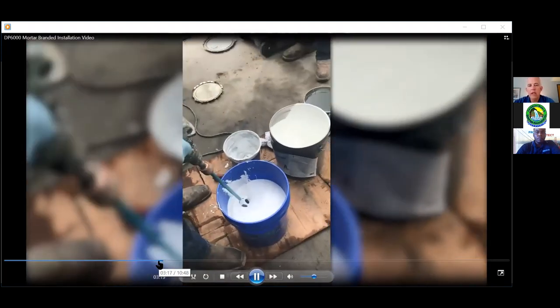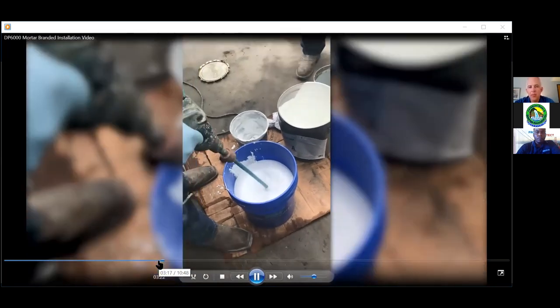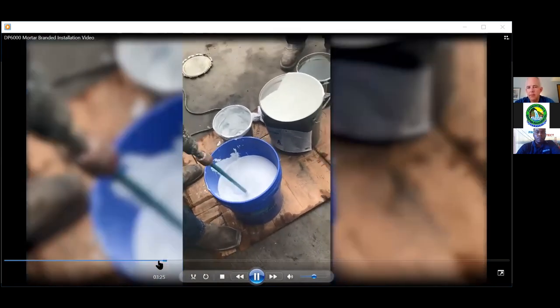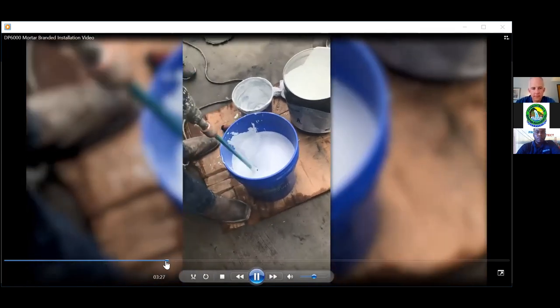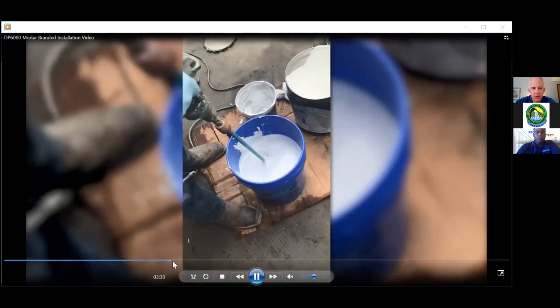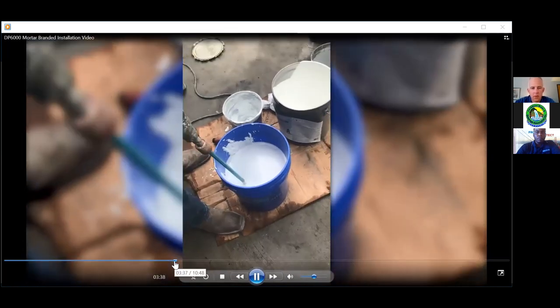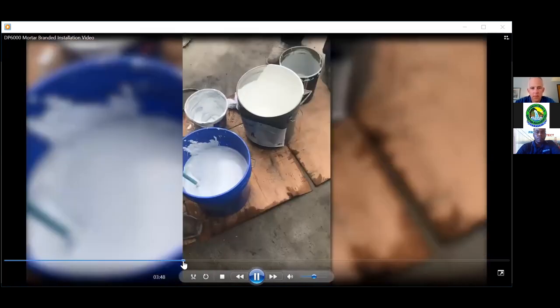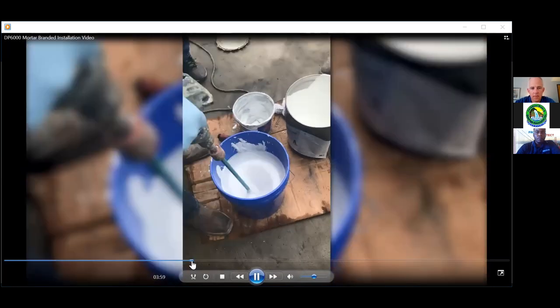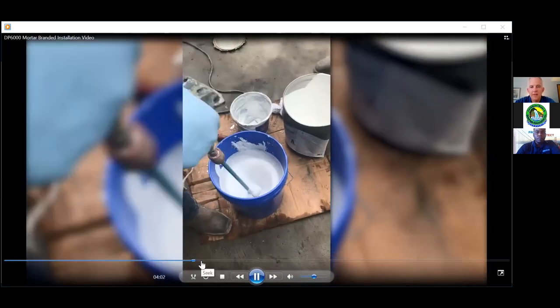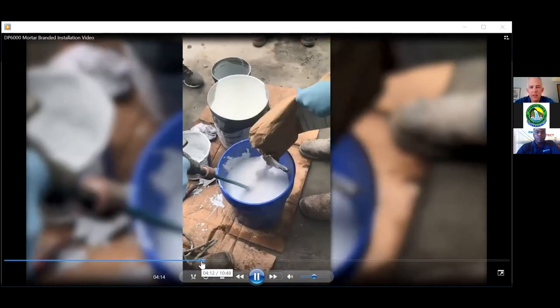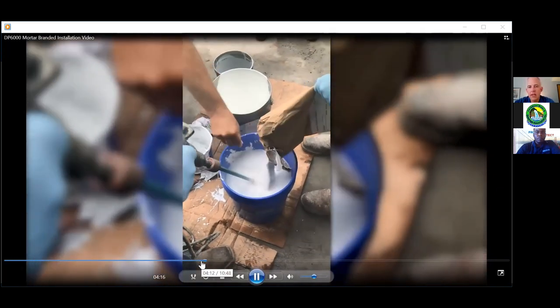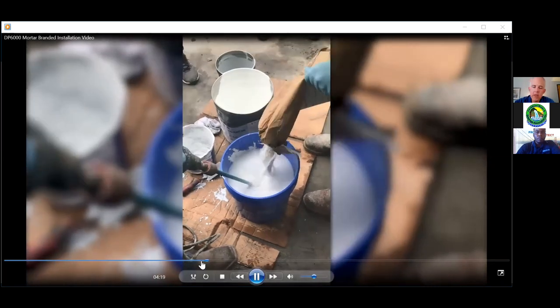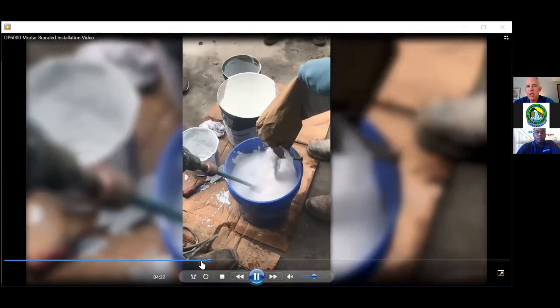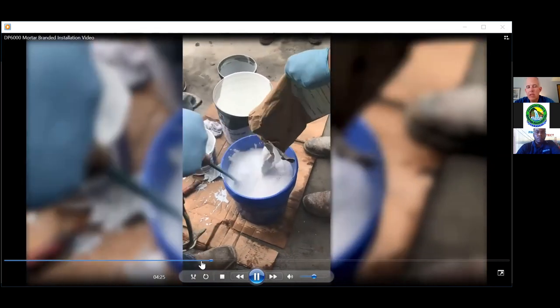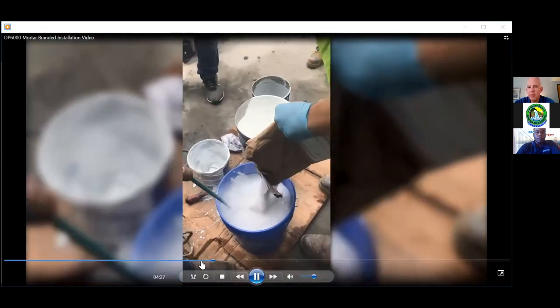So he's mixing up the liquids themselves, the part A and part B, and just getting a good mix on those. I'm fast forwarding it so we don't have to sit there and watch him drill mix. Now he's putting a sand aggregate into that liquid resin itself. And the reason we're doing this is epoxy resins can be applied two different ways. One, they can be sprayed on these structures, or two, they can be hand troweled.